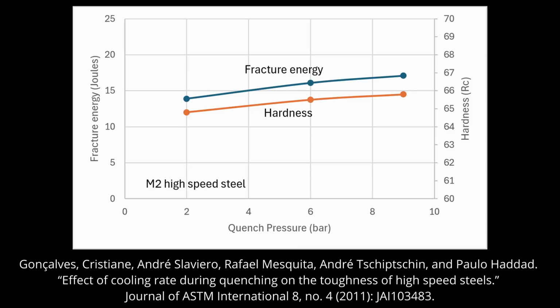With slow cooling, carbides are precipitated at the grain boundaries. This depletes carbon from the matrix, reducing hardness. And those precipitated carbides are brittle particles, and they reduce toughness, especially since they are present on the grain boundaries.